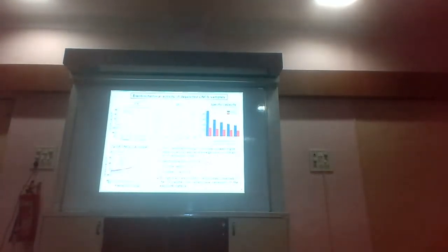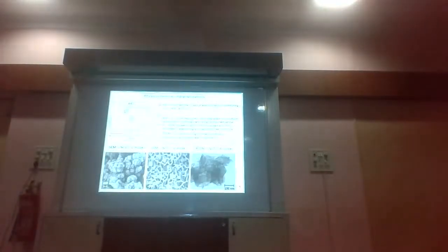It was due to the morphology. If you see the morphology in the CV mode, it was not very highly porous, only very small pores were there, and a non-uniform nanoscale morphology was there. It was not facilitating the electrolyte movement, or there may be less electrode and electrolyte interfacial interaction. Whereas in CM mode, we got a highly interconnected morphology, which could facilitate the electrolyte transportation, and the interaction between the electrolyte and electrode was enhanced.